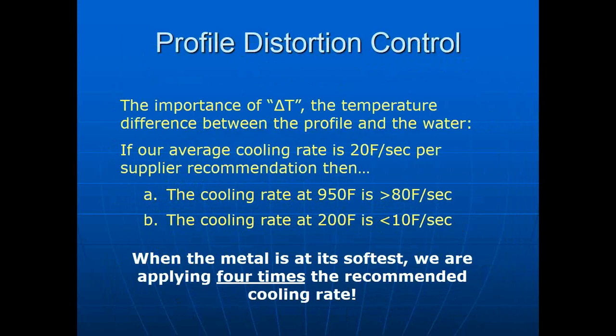The importance of delta T, the temperature difference between the profile and the water, is key to this understanding. Your cooling rate is delta T times your cooling mode, whatever that mode is. So let's just take an average cooling rate of 20 F per second. If we're averaging that across the quench, that means when the metal first comes in at 950, we're cooling it at about 80 degrees per second. And at the back end of the quench, as it's cooled off, we're cooling it at something less than 10 degrees per second. So the challenge in quenching is that when the metal is at its softest, in this illustration, we are applying 4 times the recommended cooling rate.